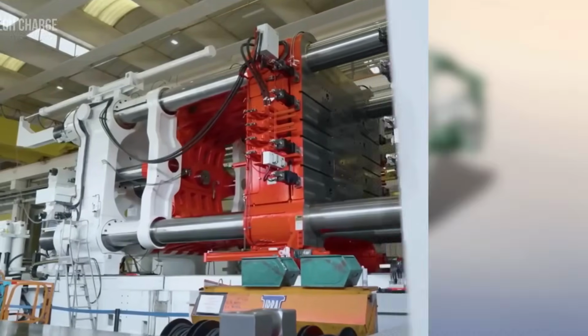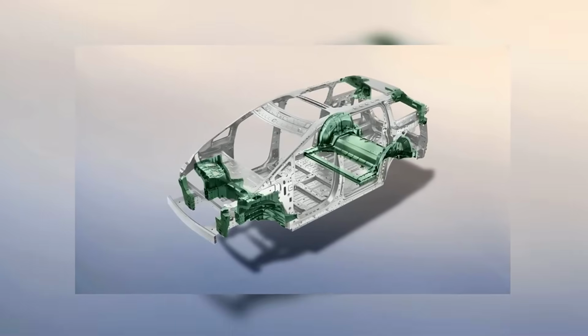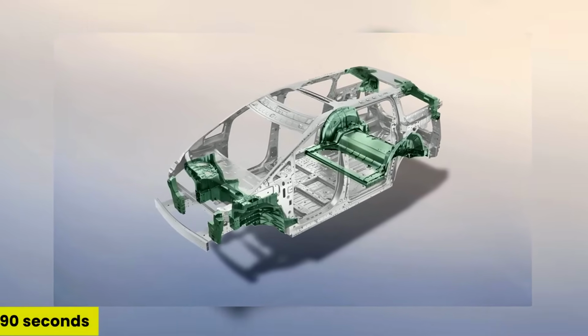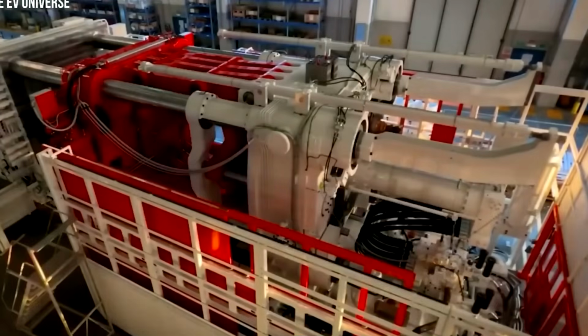The Hypercasting machine bypasses that entire sequential process. 72 isolated components instantly become a single continuous structure. 840 weak weld seams drop to zero. The complete injection, pressure holding, and rapid cooling cycle requires exactly 90 seconds.